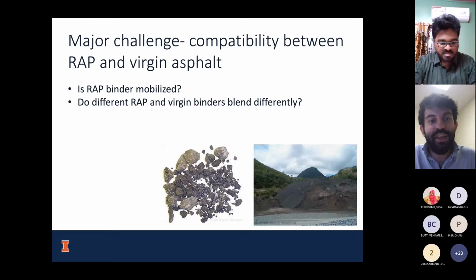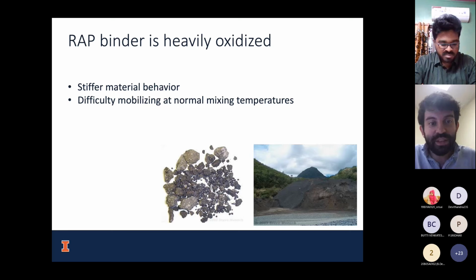But the major challenge is, is this material compatible with the virgin asphalt? So is the wrap binder in the asphalt mobilized? And do the different wrap and virgin binders blend differently, right? The wrap binder is heavily oxidized. It's more stiff. And it has a difficulty mobilizing because this material is aged, right? So that means it had some reaction with the oxygen, and now it's finding a lot of difficulty getting it to move again at normal mixing temperatures.